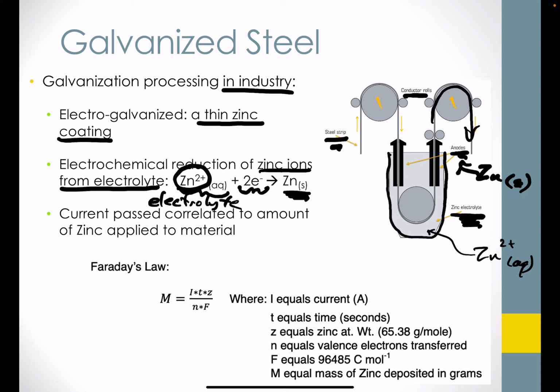What's important and interesting here about the electrogalvanization process is that the current passed is correlated to the amount of zinc that's applied. And this is calculated by Faraday's law. So here you see Faraday's law, where the mass of the zinc applied goes proportionally with current, I, in this equation. To give you further analysis of this equation, we can look at the units and the other factors. So we have t, the time of the deposition. So that could be the residing time in the electrolyte bath. We have the atomic weight of the metal being applied, in our case zinc.